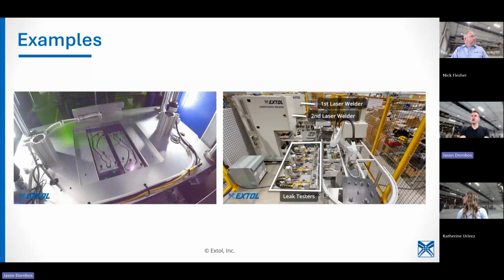Would you agree that a bigger issue would be if you have a mark on your weld profile, like an ejector pin that's pushing on your weld rib and making a 40 thou dent in the ply? That's much harder. We usually can't press that out. I actually have seen us do that. Really? I have seen us press out a knit line or a seam from a mold.